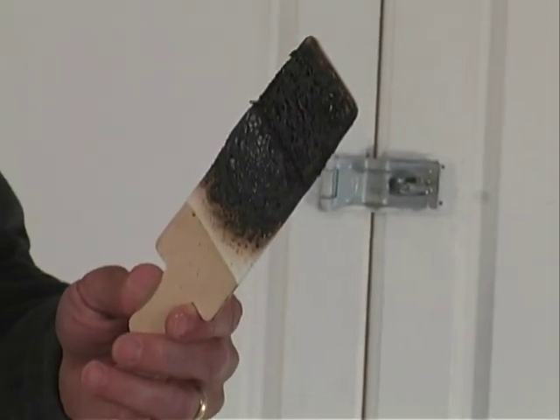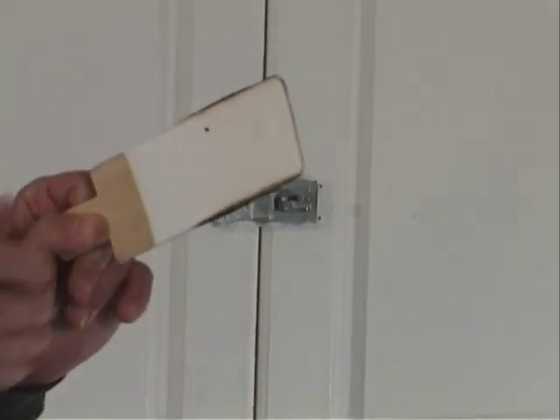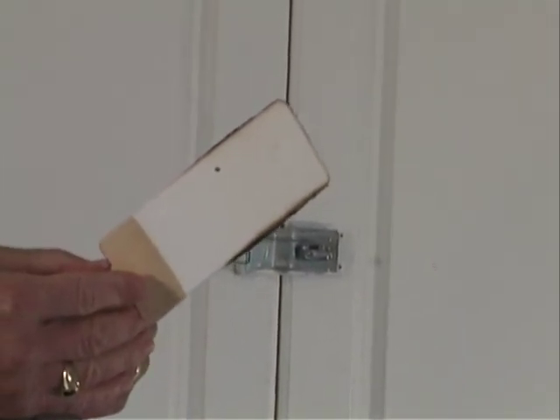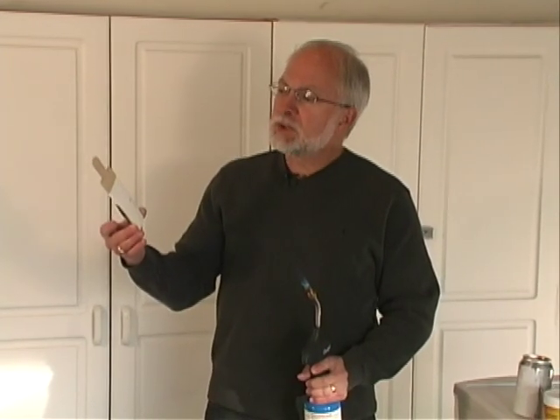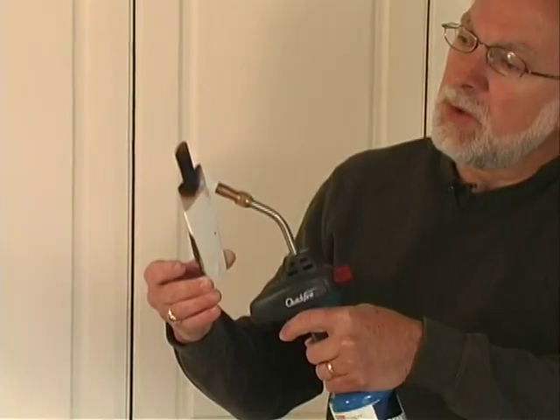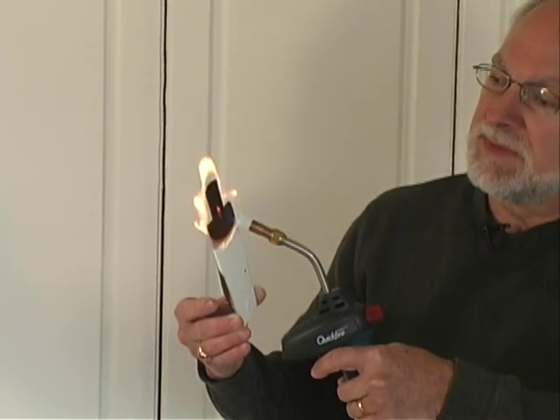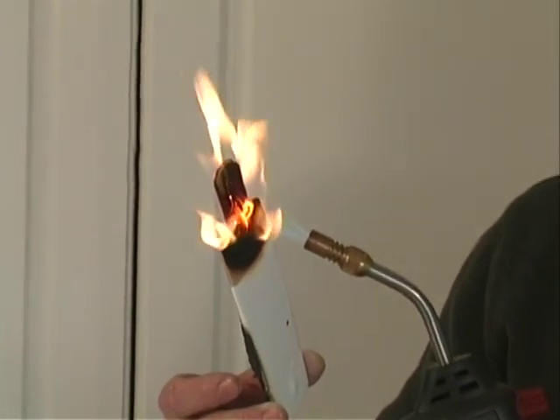Notice that when I turn the paddle over — with all of that, we really haven't damaged the backside at all. And that's in a paddle that's 3/32nds of an inch thick, identical to the one in your sample kit. Just by way of comparison, try burning an unprotected end of the paddle with the same blowtorch. Within 3 seconds, the paddle is completely charred and fully inflamed. Within 10 seconds, we're going to blister completely through it.